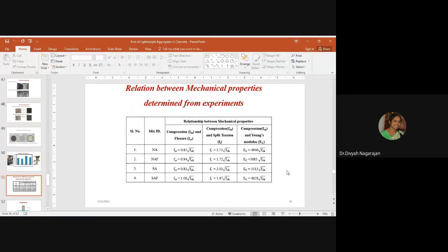Now, the relations between mechanical properties determined through experiments were correlated with various codes of practice. The relation between compression and flexure is 0.7 root fck as per IS code provision, whereas what I obtained for normal aggregate concrete was 0.85 root fck. When fiber is added to the normal aggregate concrete, it is 0.94 root fck. For sintered fly ash aggregate concrete, that is lightweight concrete, it is 0.83 root fck. When fiber is used with sintered fly ash aggregate concrete, it was 1.08 root fck.